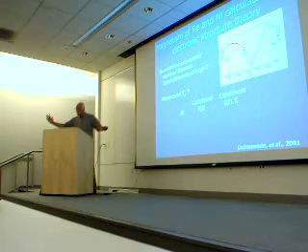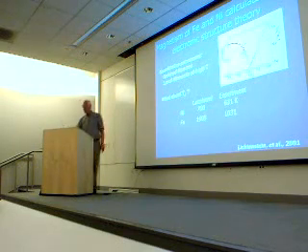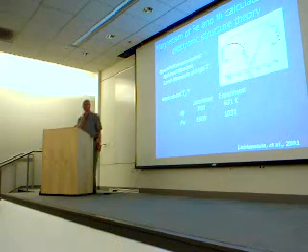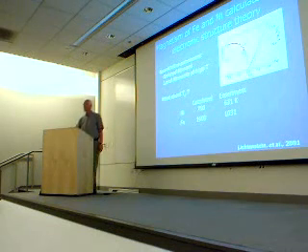And these are calculations that use parameters from density functional theory. And so the qualitative success is the moments at high temperature and low temperature. What about the actual value of the transition temperature? In nickel, it just works out marvelously with reasonable values of U. And in iron, it doesn't. The calculated transition temperature is way too high.